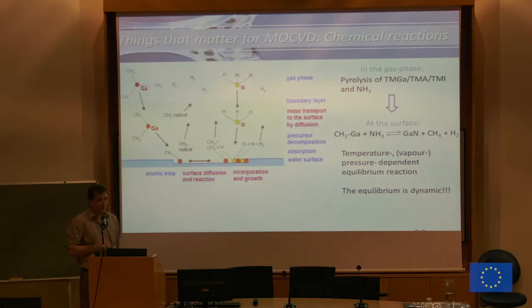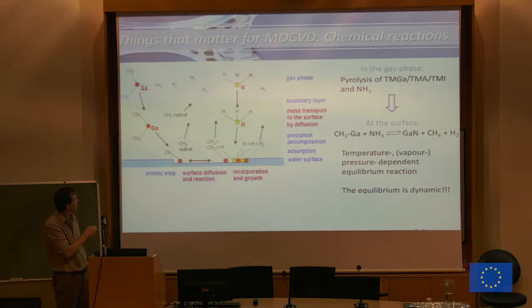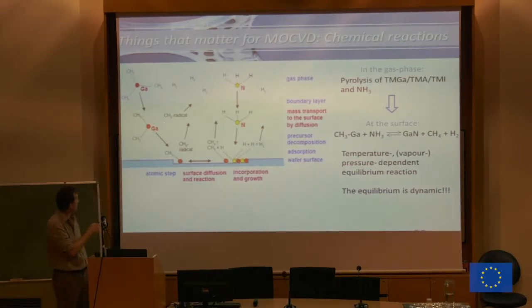So if you then turn this situation and you look at the chemical reactions, you have the boundary layer where your source materials have to diffuse through, where you also have a quite significant temperature gradient. And as the source materials, like this trimethyl gallium, diffuse to the surface, they will start to pyrolyze. So it will lose some of these methyl radicals in the gas phase because of thermal decomposition. So that on the surface, really, you end up with a monomethyl gallium and a flavor of ammonia that may be losing one of the hydrogens or not.